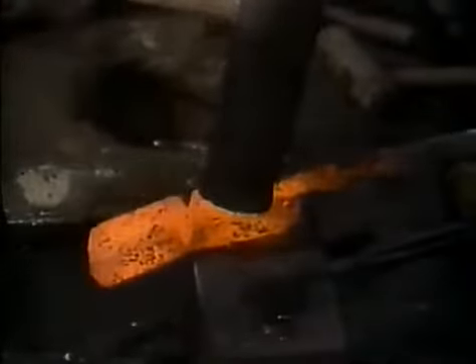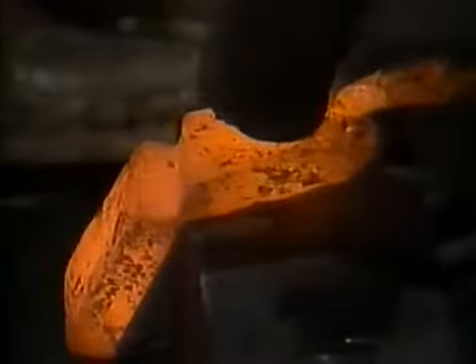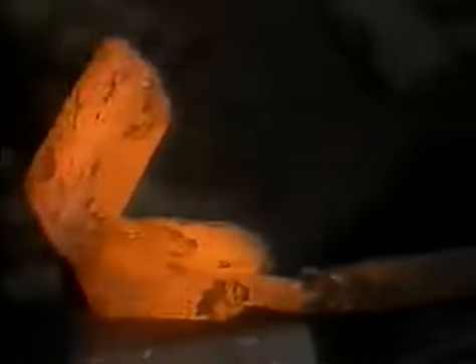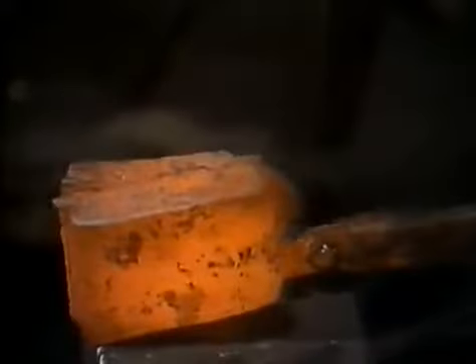Each time this is repeated, more impurities within the tamahagane, principally silicon, phosphorus, and sulfur, are peeled or scraped off, or scattered by the hammer blows. Each repeat also reduces the carbon content a fraction. To reach the correct level, the process needs to be repeated around a dozen times. The orikaishi continues, and each time the new block is wrapped in ashes and coated in the clay slurry.